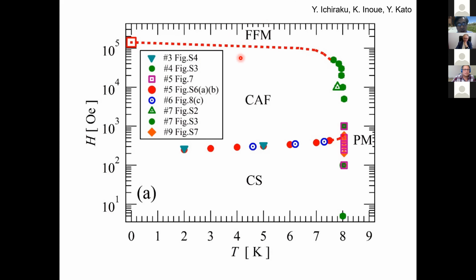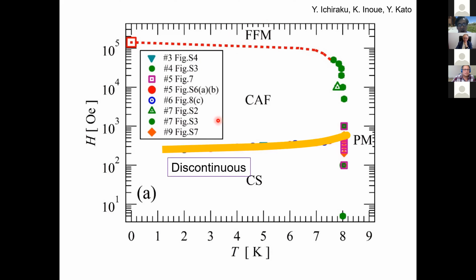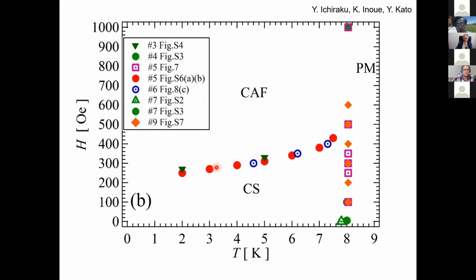The mystery is this one. This line is, if we remember, we have the peak in the chi prime and chi double prime of the AC susceptibility, and there is a peak in chi double prime between these phases. This means this borderline is a discontinuous borderline. This is a phase transition. The curvature is like this. This is a downward convex curve. This phase transition line.